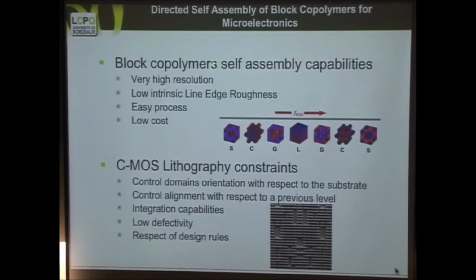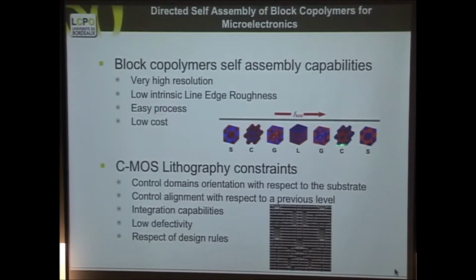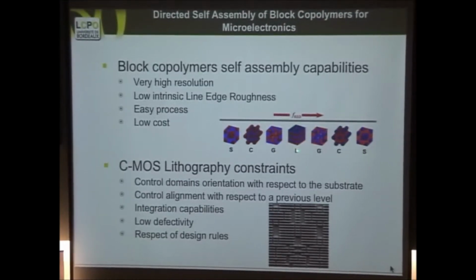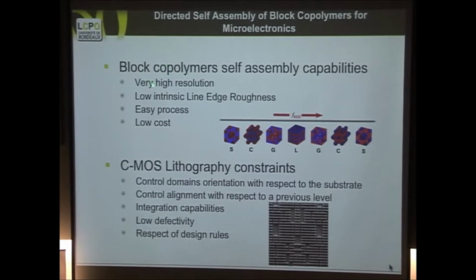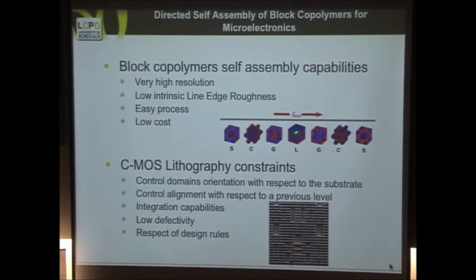So ultimately, you see here that these kinds of systems we know how to fabricate, we know how to synthesize, we know their behavior theoretically, so we can go and build molecules exactly the way that we want. So we can reach very high resolution, because the features that we can have here depend on the molecular weight. So we can go from 5 to 1,000 nanometers if we want, depending on how big this molecule is. So we have low intrinsic line edge roughness, meaning that the interface between the 2 blocks is very sharp, because the 2 blocks are separating, they don't like each other, so this interface is very sharp, and it's a condition that's required for the electronic industry.